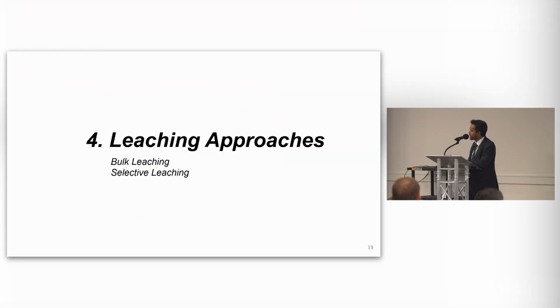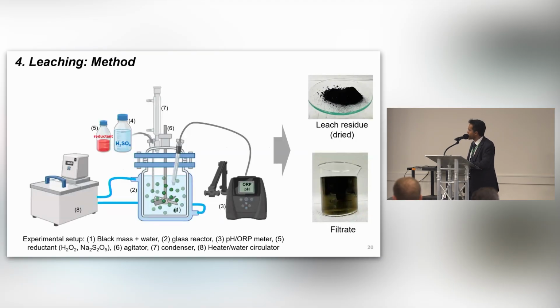So now I'm moving into the leaching approaches. Here we tried two different types of routes. The first one is bulk leaching. In the bulk leaching, we try to dissolve all the critical metals, lithium, nickel, and cobalt, into the solution. And in the selective leaching, we targeted the dissolution of specific critical metals. This is the experimental setup that we use for our lab-scale leaching, and we measured the ORP and pH variation during each reaction. After the leaching, we filtered, and you can see the filtrate color is a little bit dark green. That's basically because of the high nickel.